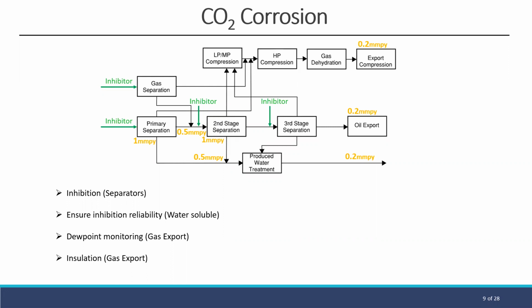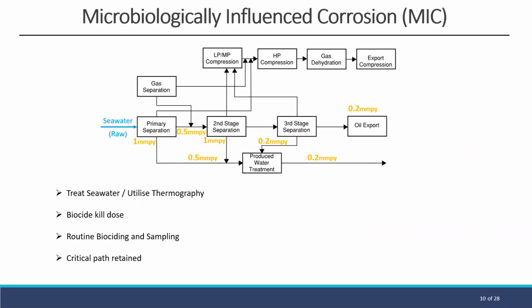inhibition of the separators to ensure carryover throughout the rest of the stream. Additionally, a review of the inhibitor to ensure it's water soluble is recommended. The corrosion rates are most prevalent at separation and diminished downstream. And moving on to the export system, what we recommend is dew point monitoring, and where there are prolonged periods of excursions, potentially insulating these items. Now, I know what you're thinking, mitigating against CO2 and introducing the potential of CUI. However, this would be managed through the CUI strategy.